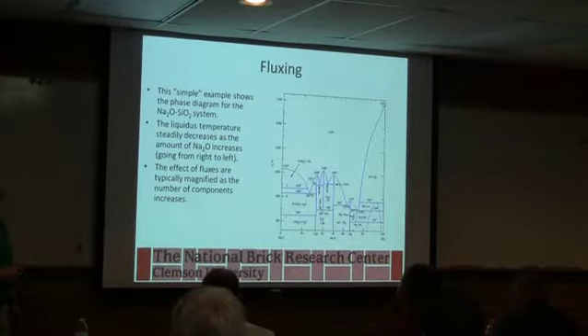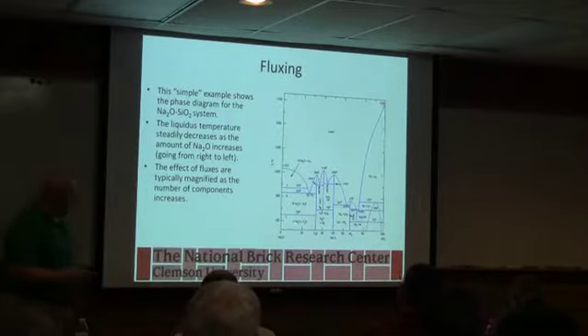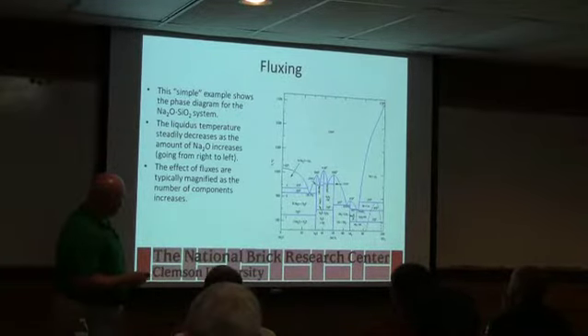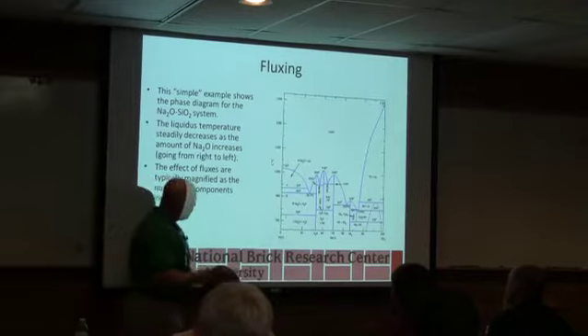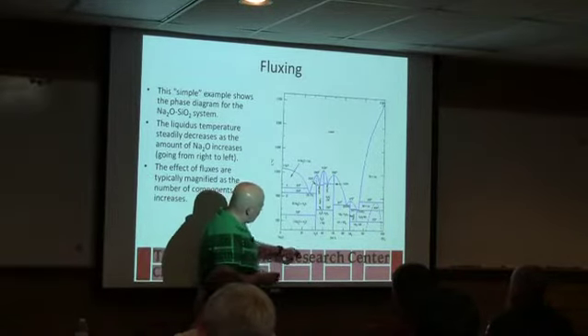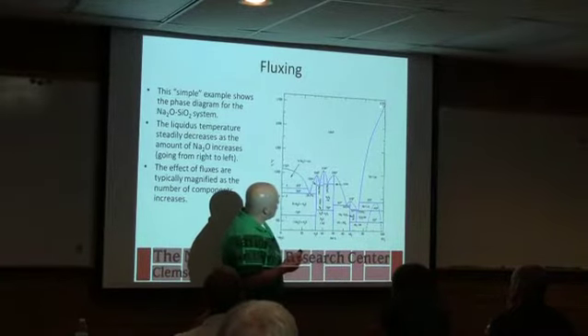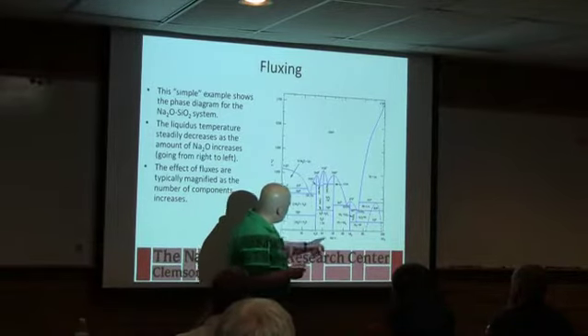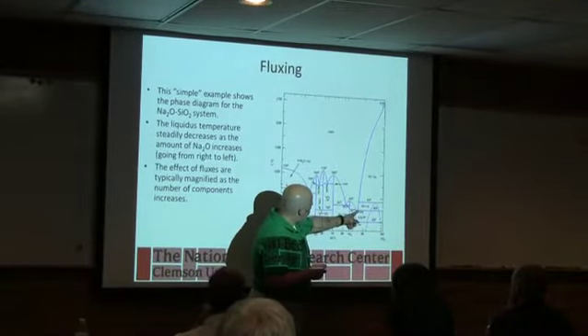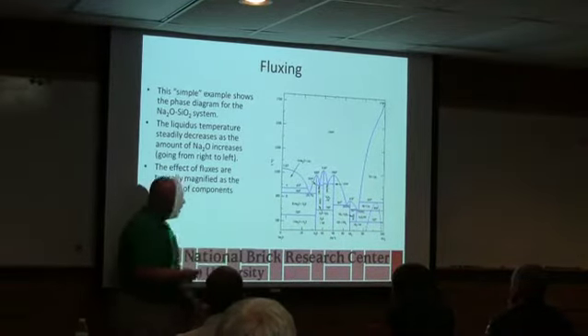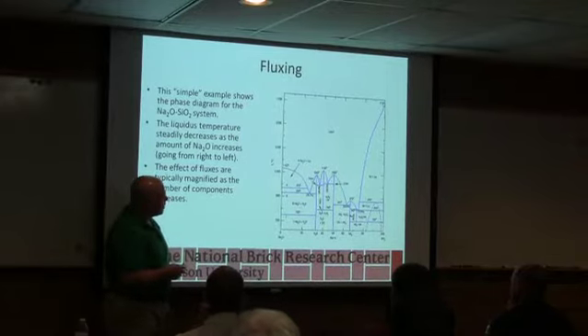That's kind of redundant. This is what we call a phase diagram. I was trying to show here what happens. If we take silica by itself, to get glass or liquid formation, we've got to get it up to 1723 Celsius, really hot, to melt sand. When we start adding sodium to it, you can now start to see your first liquid in the 800 degrees Celsius range. So just an idea of how powerful fluxes can be.